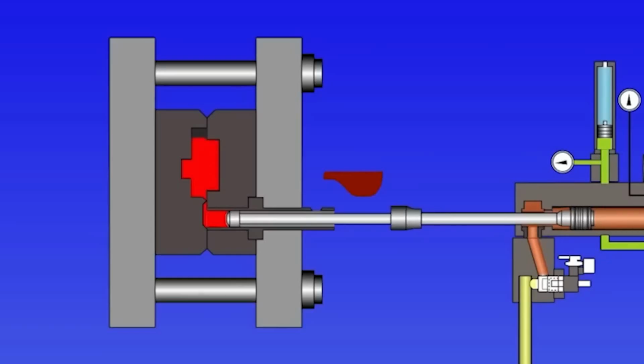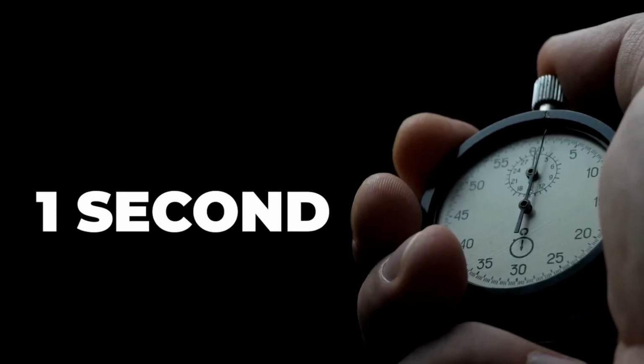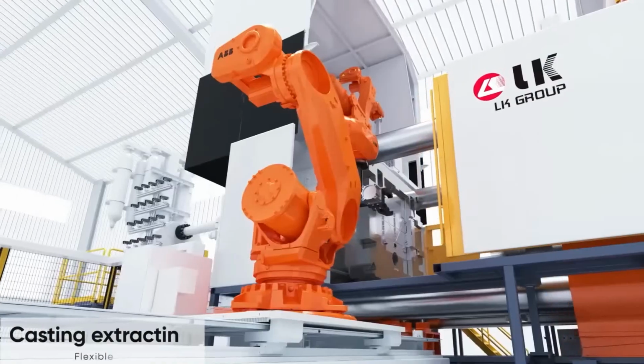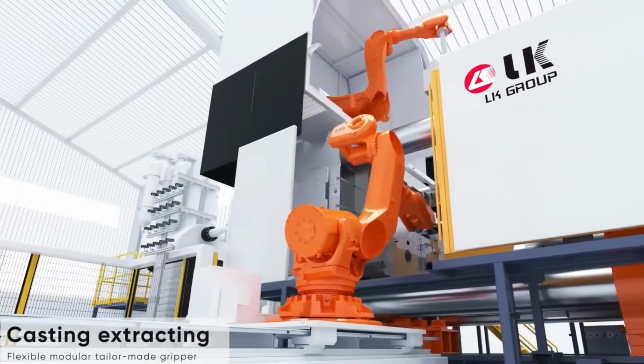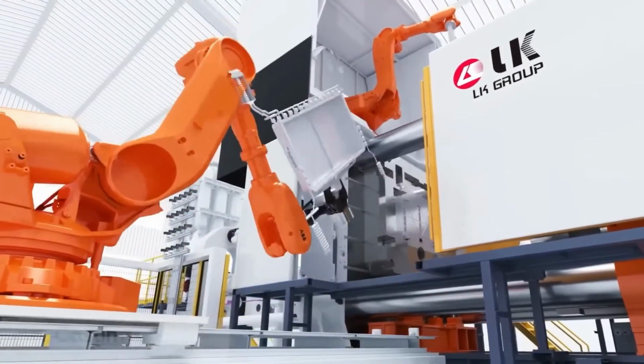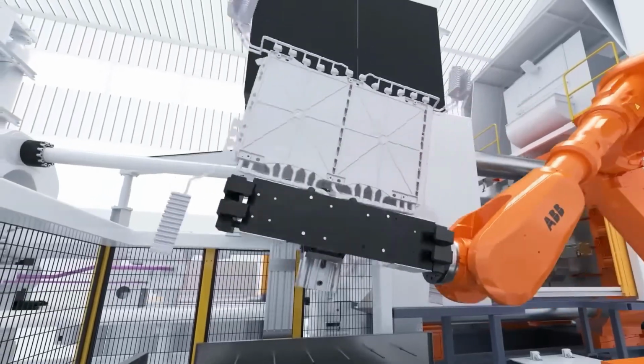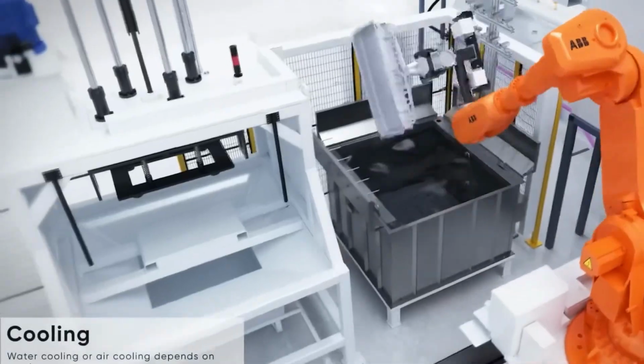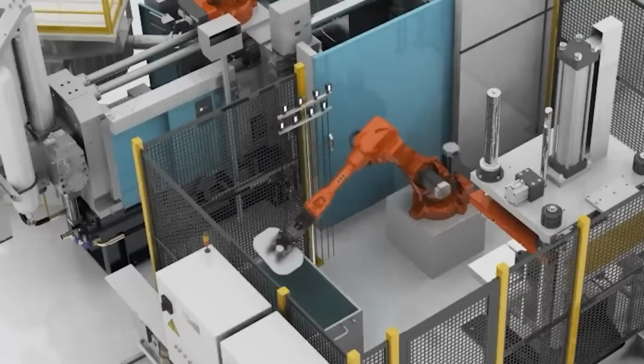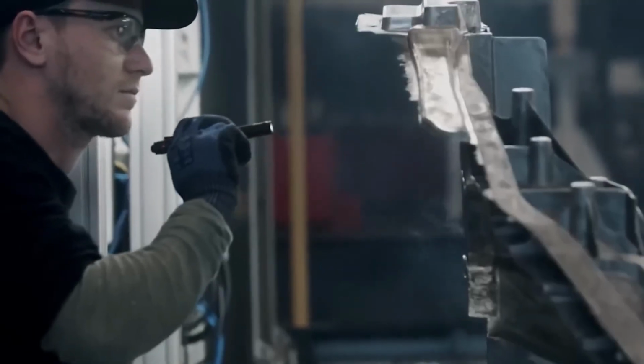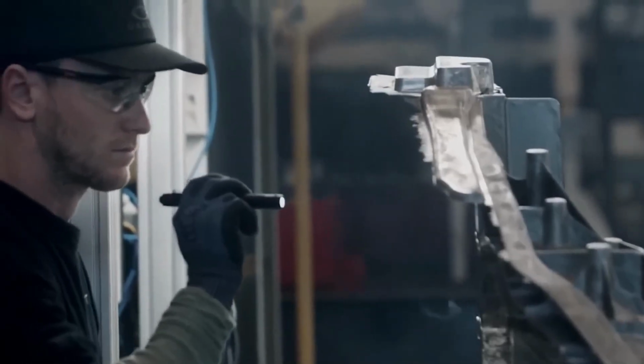The Giga Press is an all-in-one casting solution. It features a melting oven that will liquefy solid aluminum at 1,500 degrees Fahrenheit. Then the mixture is purified by removing the slag, or aluminum oxide, from the top. The molten aluminum is then treated with argon gas to further remove impurities and moved through a silicon carbide filter to eliminate any remaining particles larger than 25 micrometers.